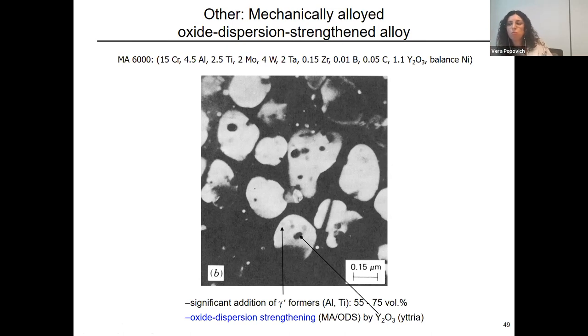But what's the other approach that is done is oxide dispersion strengthening. So yttria oxide, you see this yttria oxide that is also added into this mixture. And there you can see these dark particles, also submicron, really submicron. Look at the scale, we are really zoomed in. And they are used especially to tackle higher temperature properties.